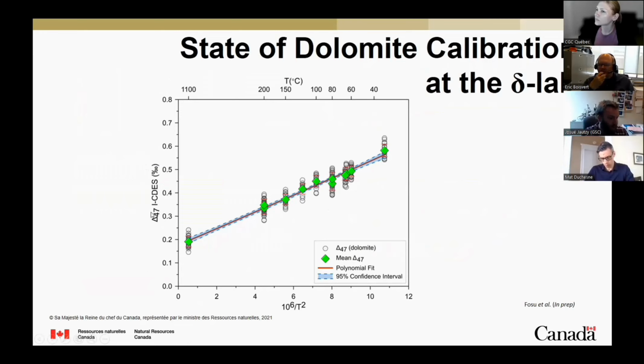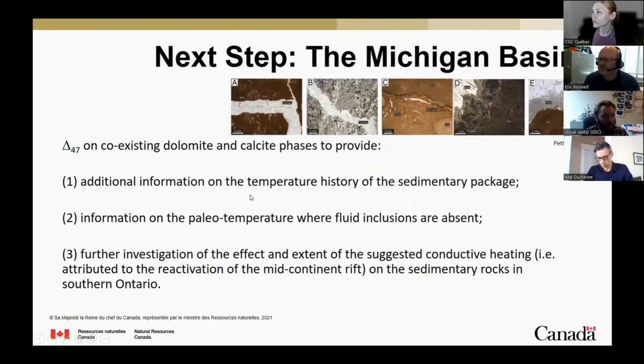You see on the y-axis the abundance of clumped isotopes. On the x-axis is the inverse function of temperature. And we have a nice mathematical relationship, which tells you that if you can measure this, which we can now, we're able to back-calculate the temperature of precipitation. So we're now spanning from below 40 degrees Celsius at the low end of the thermometer up to 1,100 degrees Celsius. So we're ready to jump into the Michigan Basin now, and stay tuned. This is going to come this year.